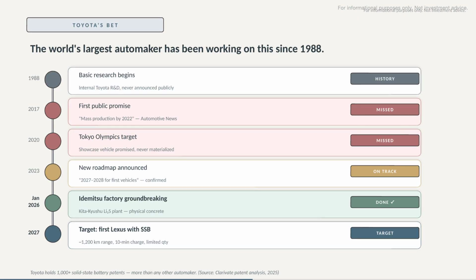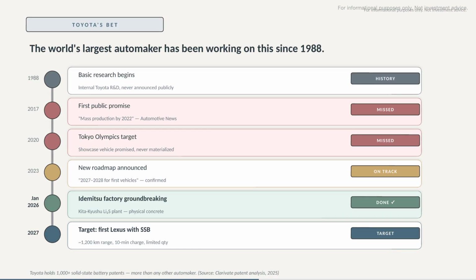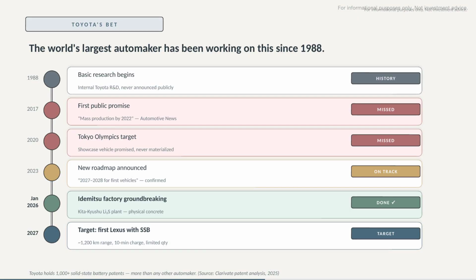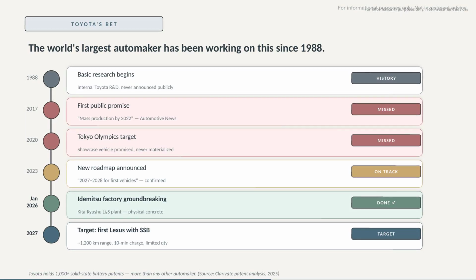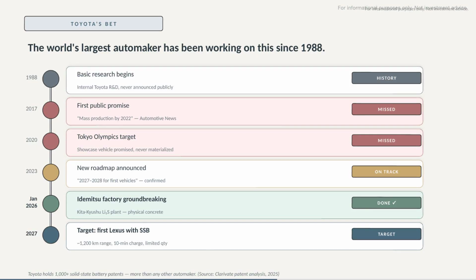Idemitsu broke ground on a lithium sulfide plant in Kita, Kyushu. Not a press release. An actual construction site. Target, mass production of sulfide electrolyte by 2027, feeding limited Lexus models with 1200 km range and 10-minute charging. Toyota holds over 1,000 solid-state patents, more than any other automaker. They've been quiet because they've been working. The difference this time, there's concrete in the ground.